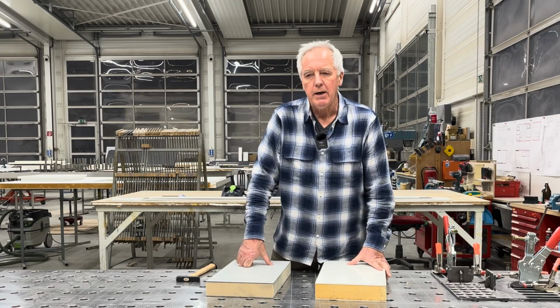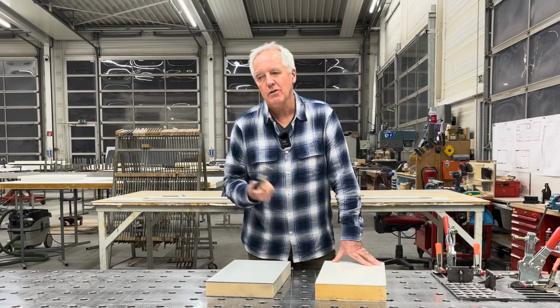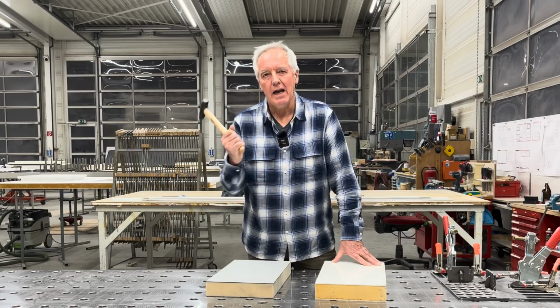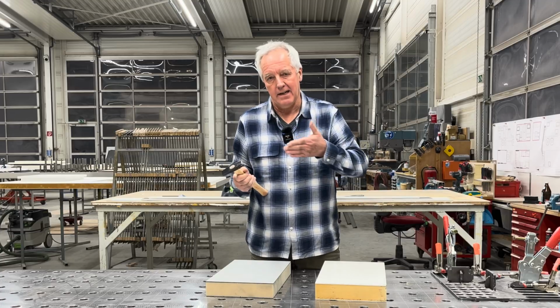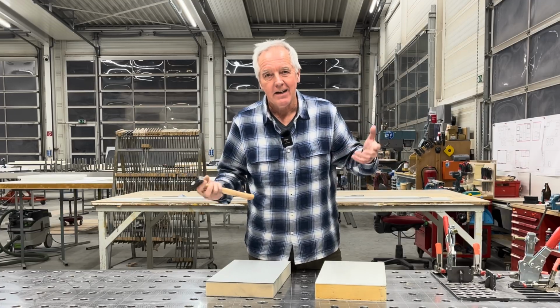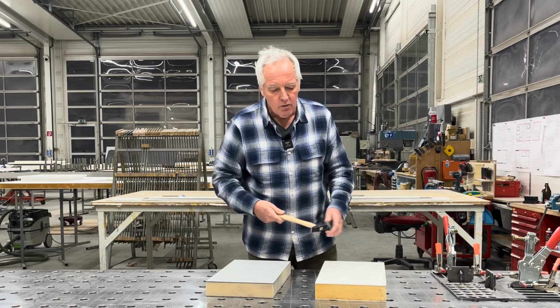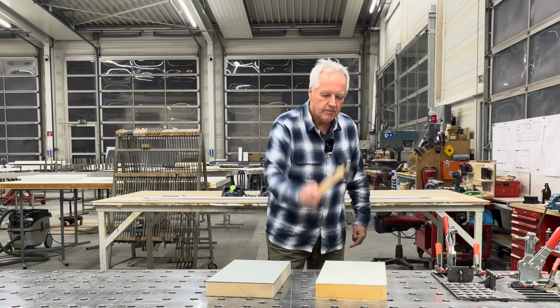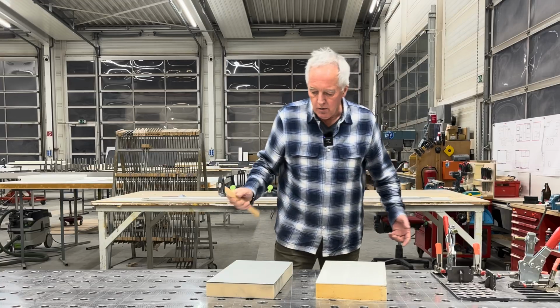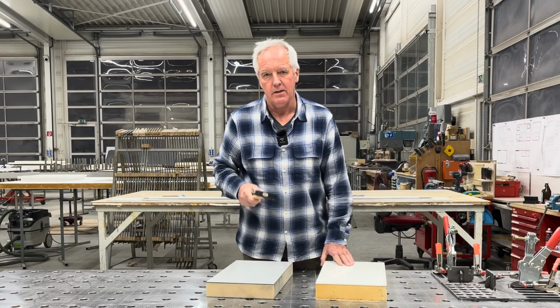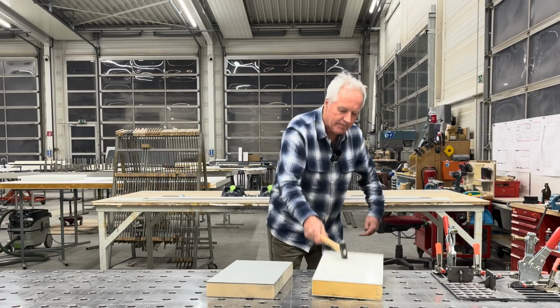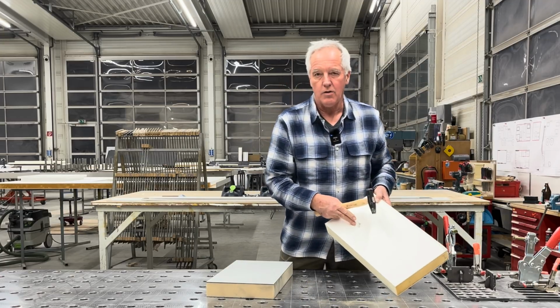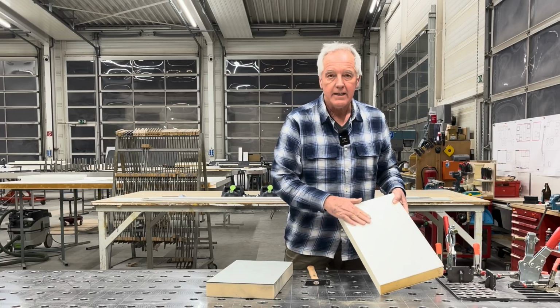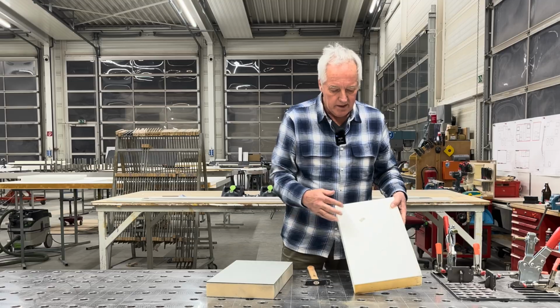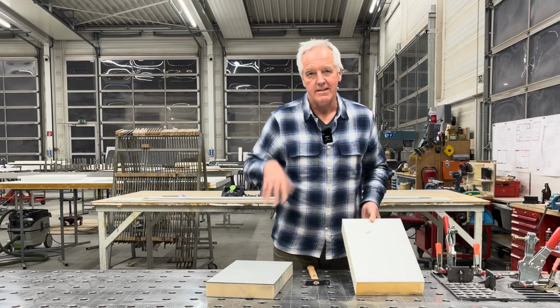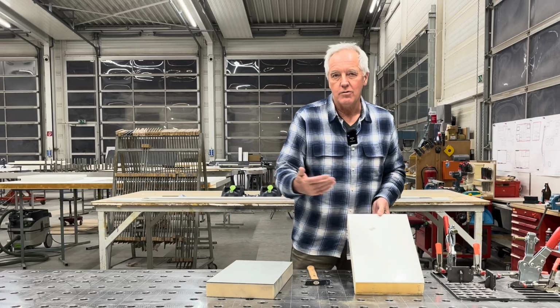Yes, but if you hit an aluminium panel with a hammer, I don't have one here, and I actually don't want to do it, you have a dent in it, and it will be very difficult to get the dent out. I mean, if you roll the truck, the dent can be very big, and the whole structure of the body is gone. Now, if you have a fiberglass panel, and the carbon is even stronger, you have to do a lot before you can really hurt it. But if you hurt it, I do it with the corner here, okay, then your impact is just only here. So if you have a hole like this, you fill it with glue and it's done. Or in the beginning, you put a piece of tape over it, and probably this stays for years because it just works until you have a good chance to repair it and get some paint on it.